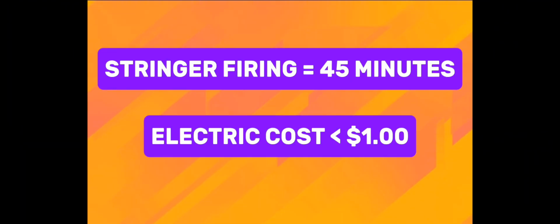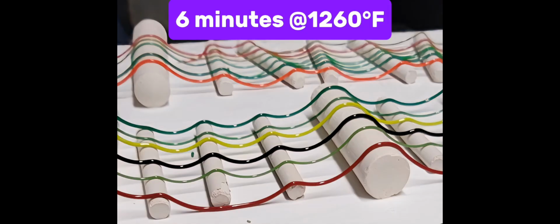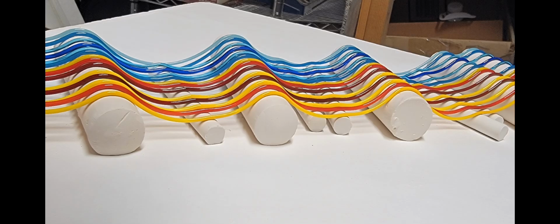Firing stringers usually takes about 45 minutes, and in my Ken 16 costs less than $1 in electricity cost. I fired all of these stringers for 6 minutes. Your kiln could fire differently, or you might want to fire longer, up to 10 or 12 minutes for more dramatic waves. The actual time you fire will depend on the size of the chalk, the spacing between the chalk, and the desired drape. Be sure to test before committing, and you can always fire again if you want more dramatic results.